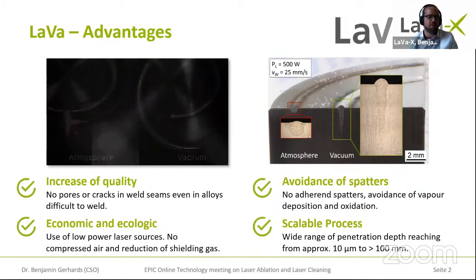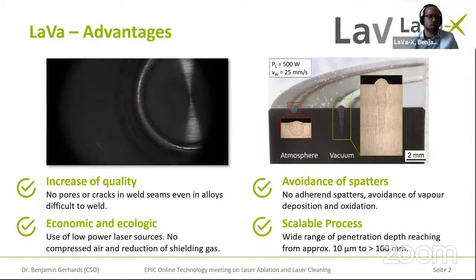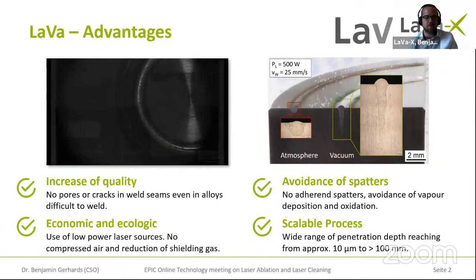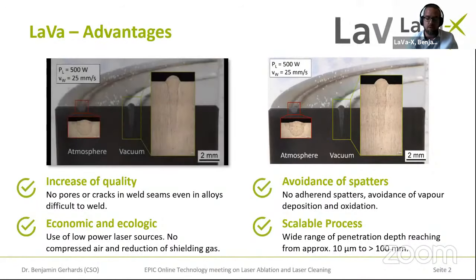And we have a very economic and ecological process because we have low laser power machines, and we can achieve the same welding result with lower power. Also, we have a very scalable process, so it's possible to weld foils of 10 microns thickness and go up to a penetration depth of 100 millimeters in steel, for example.